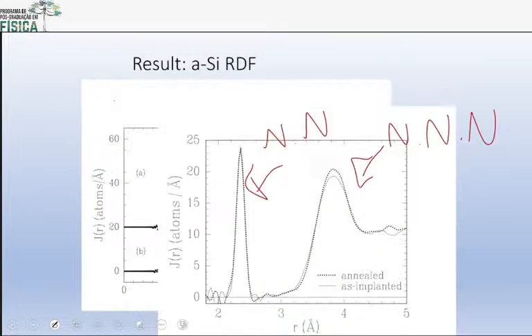So when we did this measurement, we were able to go out to high Q and Fourier transform and get this excellent resolution. And we were able to see the nearest neighbor of silicon and show that it's very well defined, even though it's amorphous. And that's telling us that every silicon atom has a well-defined distance to its neighbors. And the area under the curve tells us how many neighbors it had. And by the way, the width of this peak tells you about the bond angles.